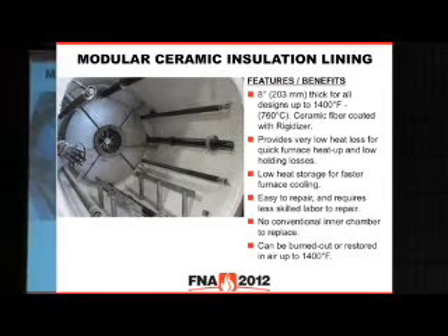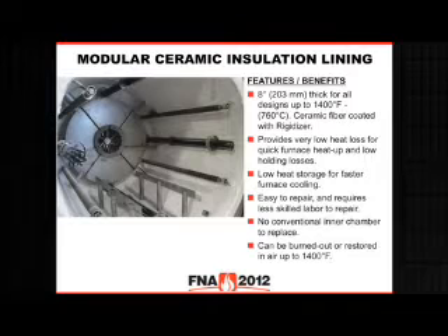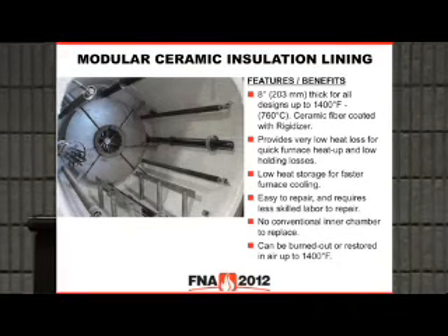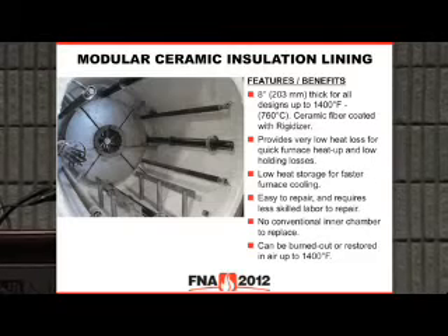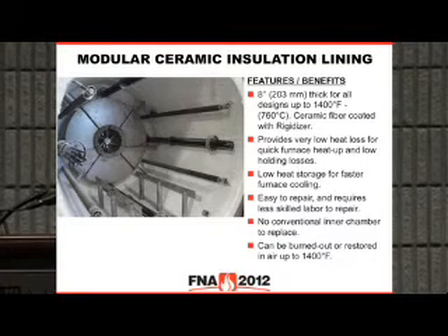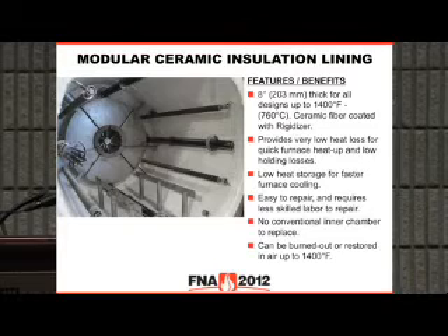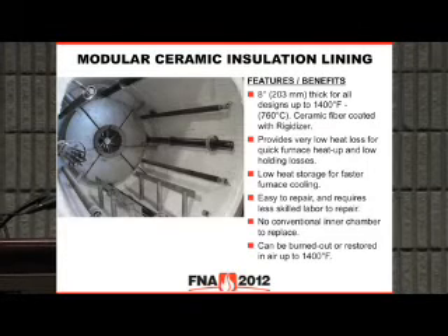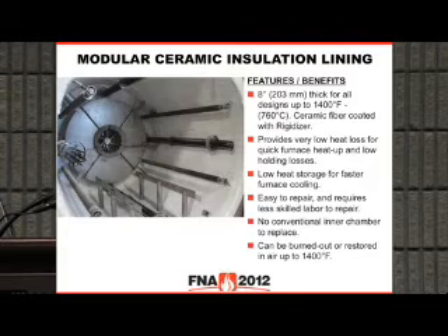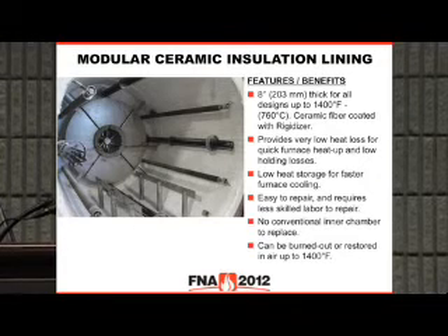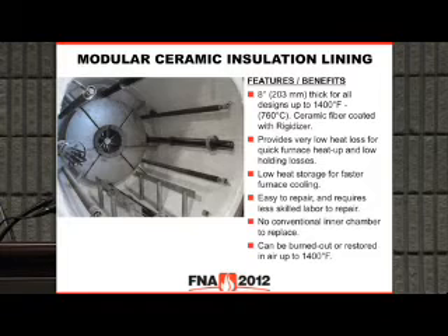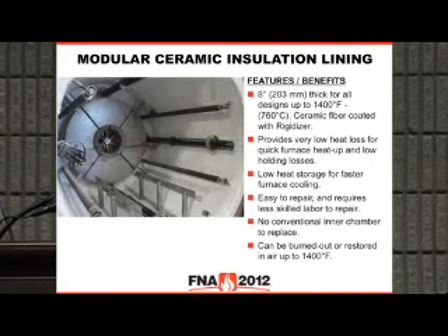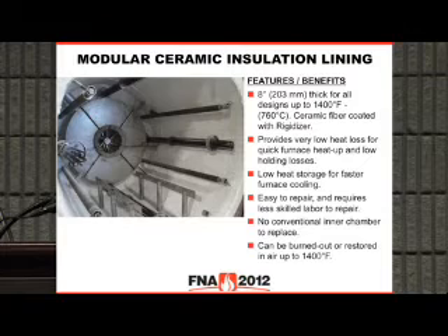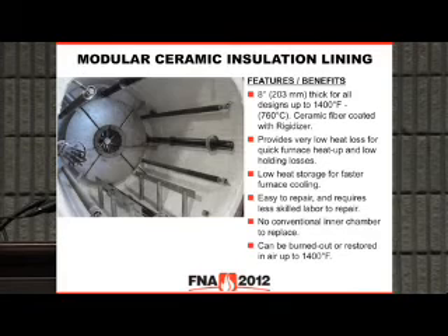Inside, we build a ceramic lined using a 8-inch module, and these have a stainless steel rod that is welded to the casing. I don't want to say it's a lifetime insulation package, because all of a sudden at some point in time it wears out and somebody's going to come and say, you said lifetime. But the systems that we have sold dating back to 1990 all have their original insulation package in them. So those are welded blocks, and then we put a rigidizer on them, which keeps wind during heating and cooling from eroding the surface of that. Keeps any fibers from wanting to radiate out.